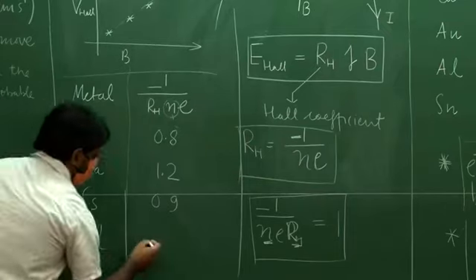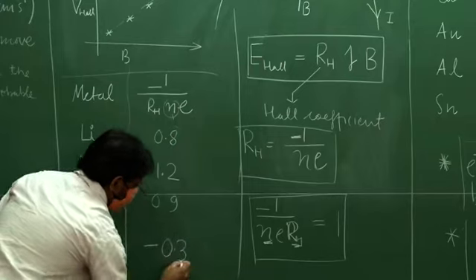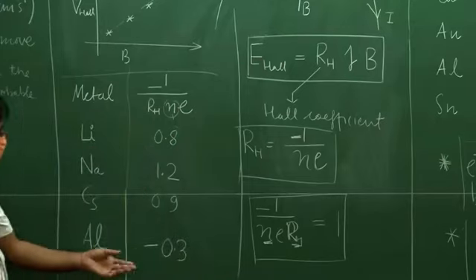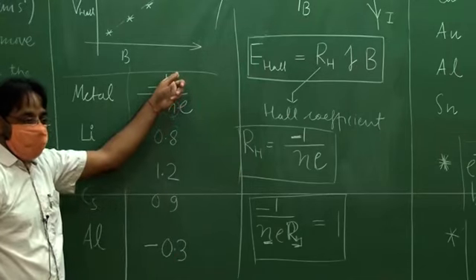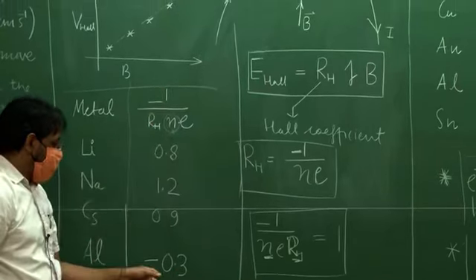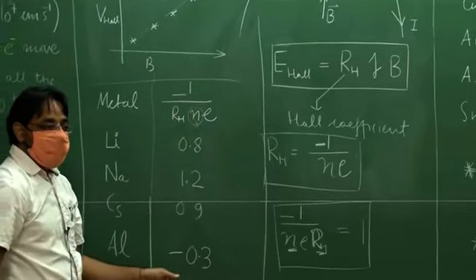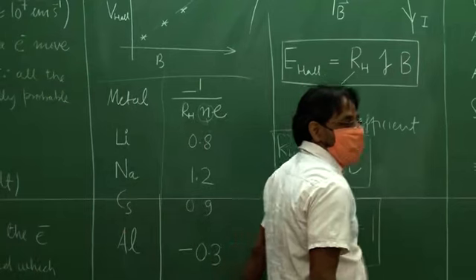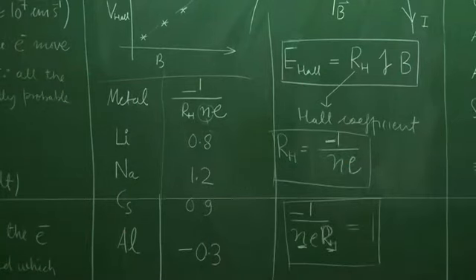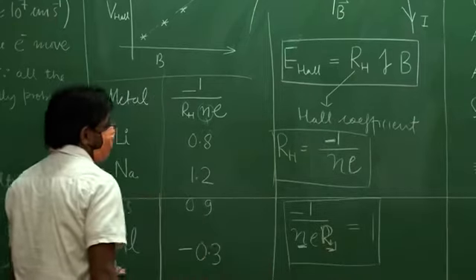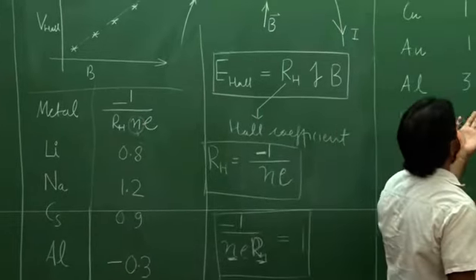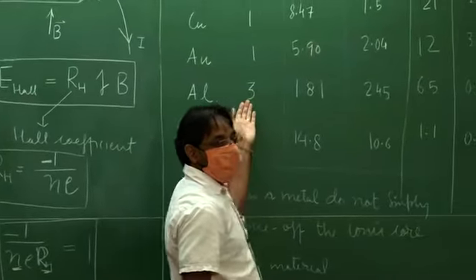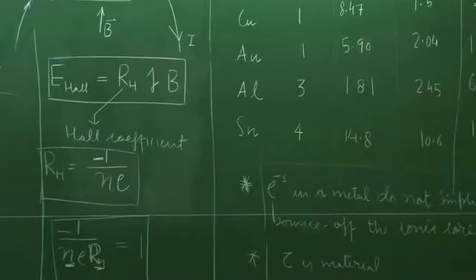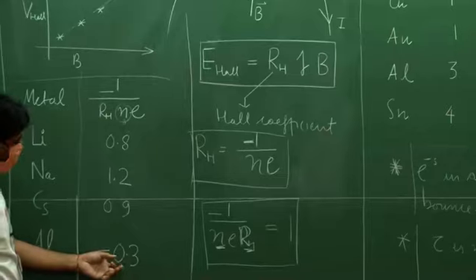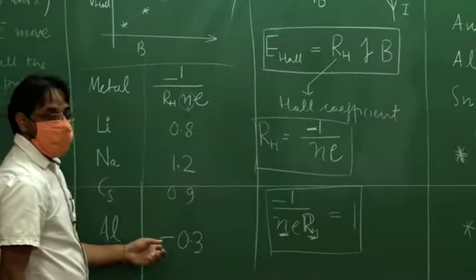Why? Because this quantity comes out to be minus 0.3. Remember what I told you, it not only departs from 1 considerably, that is one of the issues. The other issue is that it carries an opposite sign. A sign that tells you that the majority carriers in aluminum are not electrons but holes. Now, of course, this is very difficult for you to envisage, how come aluminum, which gives 3 electrons, not 1, not 2, but 3 electrons to the conduction band, has a Hall coefficient which is positive, a sign which is opposite to the sign that you expect from other, regular metals.